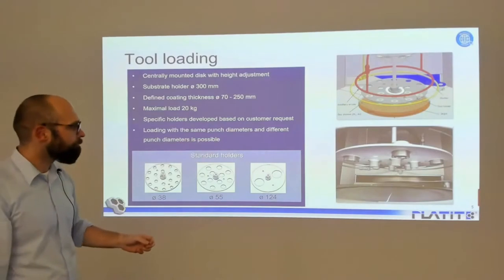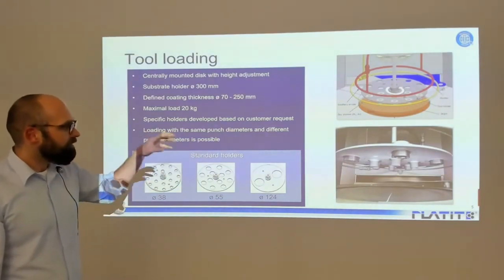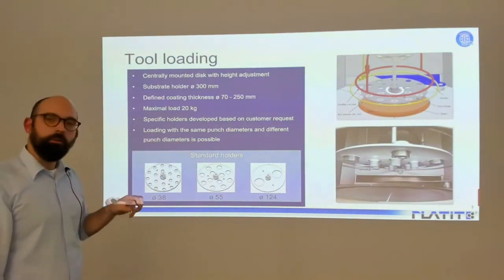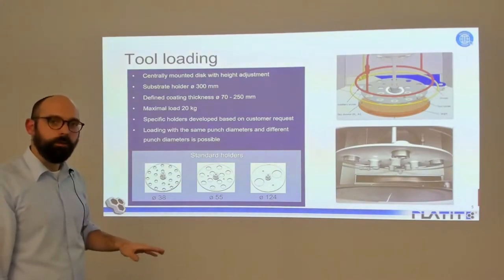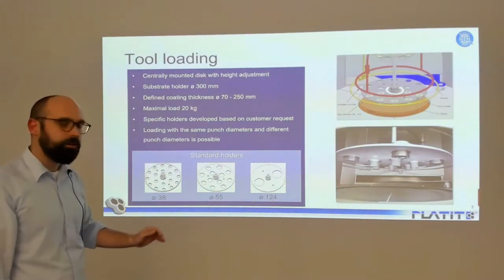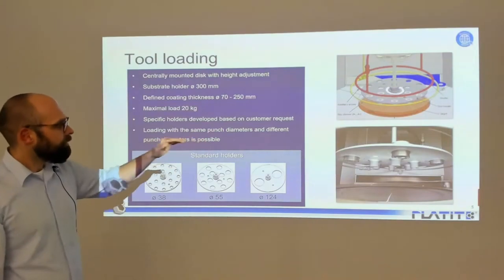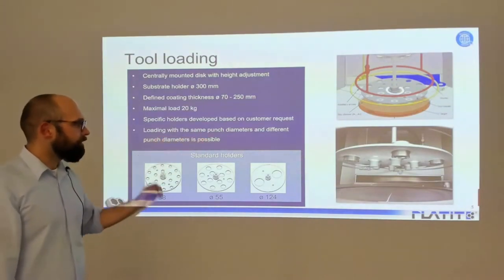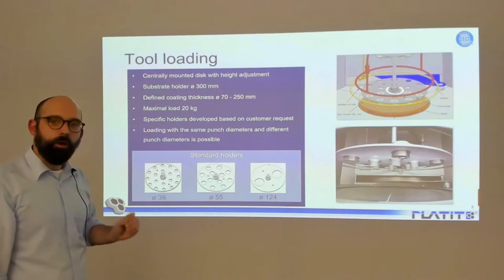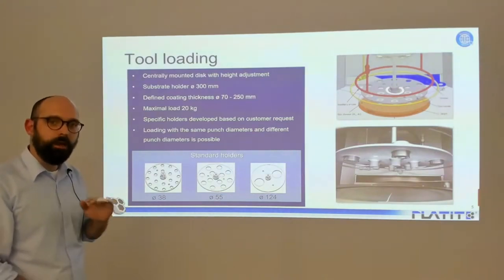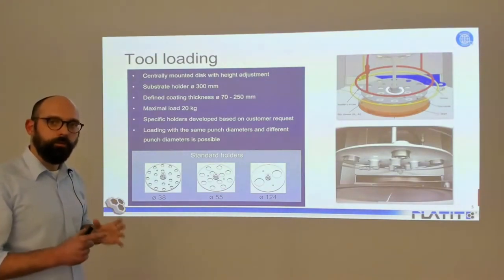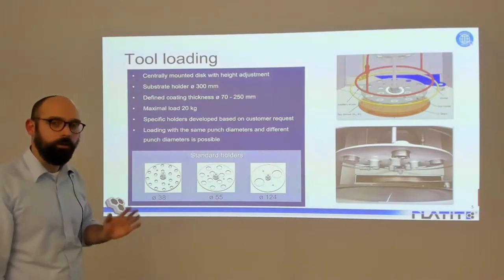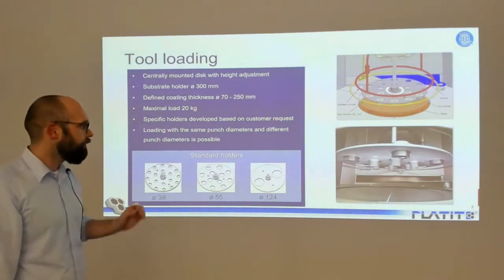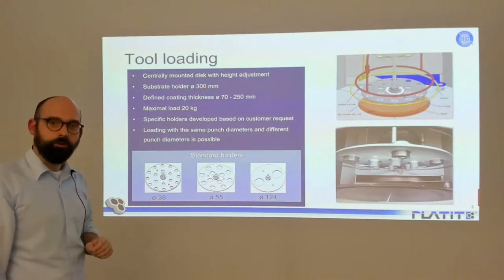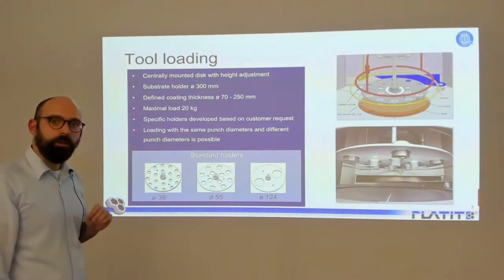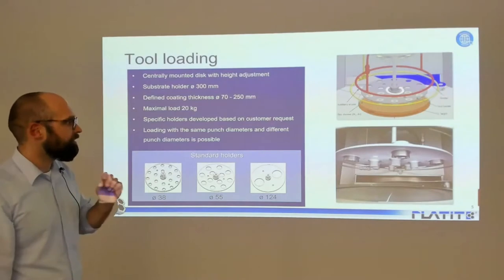on the lower right. You can load stamps with different diameters within one batch. That's absolutely no problem. The only thing you need to take care about is that the level of the area you want to coat is approximately the same for all your stamps. So if you have a very large or long stamp, you may want to put a spacer ring above. Don't worry, we also supply you with these. Then you're basically finished with loading your tools. All that's left to do now is close the vacuum chamber and press the start button.